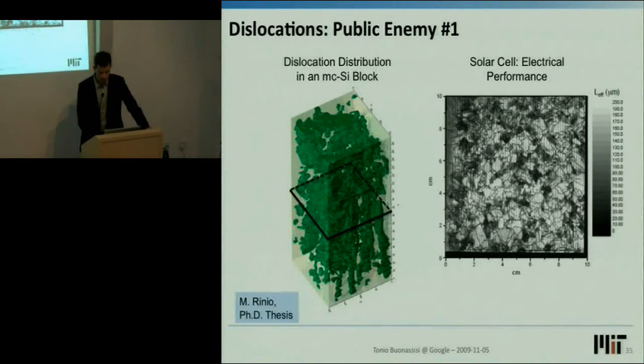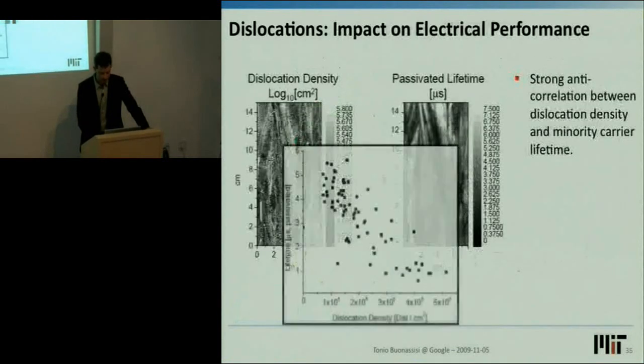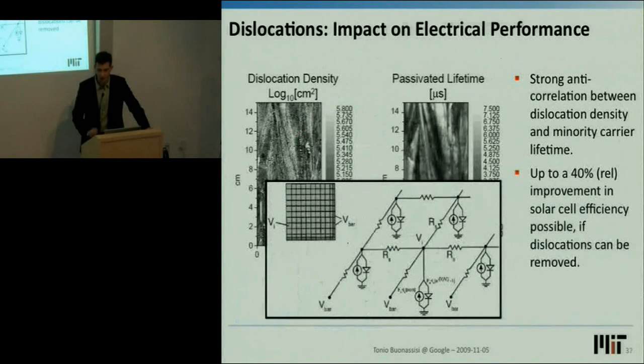And what that means from a practical point of view is that if you have the good regions and bad regions all connected together through a parallel circuit through the front surface emitter and the back surface metallization, the bad regions will drain current from the good ones, and the overall performance of your device will be reduced. So these dislocations are public enemy number one in terms of solar cell performance.